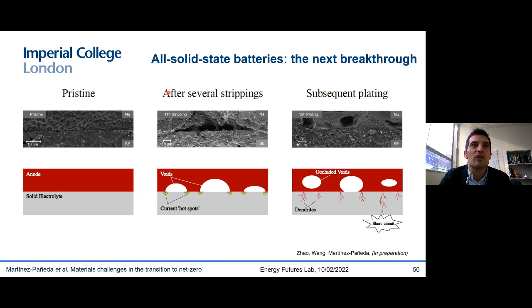You can see this pretty well here with this sketch and also these experimental images. So every discharge cycle, what you see is a stripping. That is lithium being removed and voids appearing, right? You see the voids here. And every charge cycle, what you see is plating. That means lithium being deposited and those voids reducing in size and occasionally becoming occluded from the interface. You can see this here.